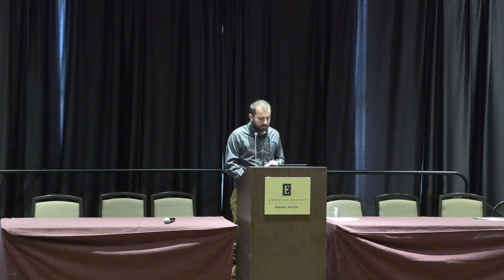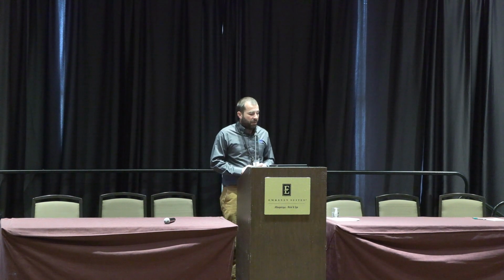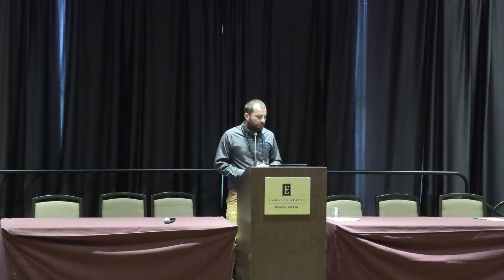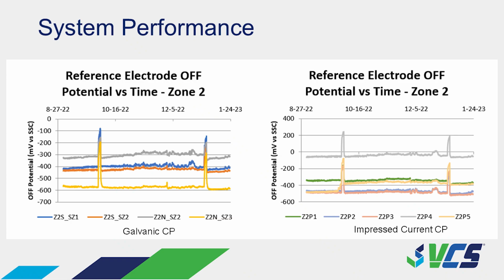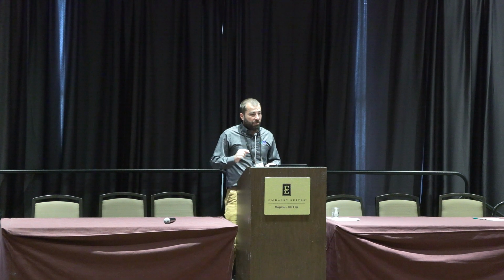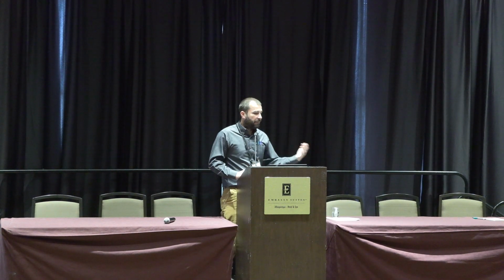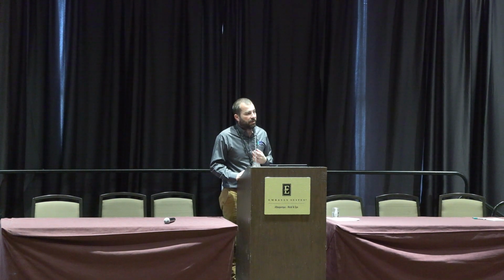With the remote monitoring technologies, we have continuous data coming wirelessly from all those zones. You can see the one on the left is the galvanic, and the one on the right is the impressed current. Then you see where we have reference electrodes embedded in concrete, and periodically we're depolarizing the system to see that it meets the NACE criteria. You can see those little spikes that happen every couple of months. Those are little depolarizations to verify the criteria is being met for NACE cathodic protection.